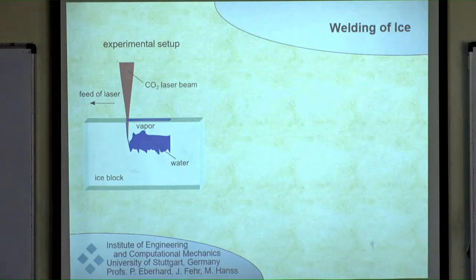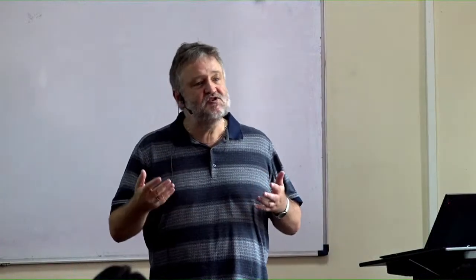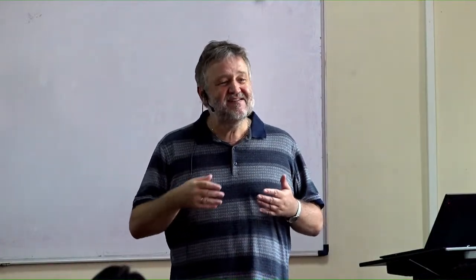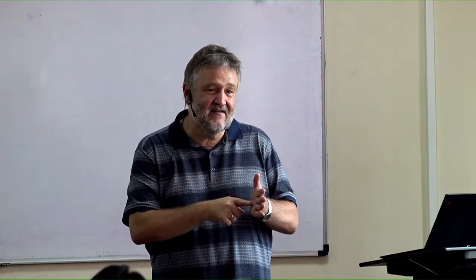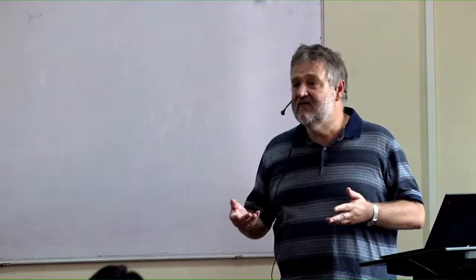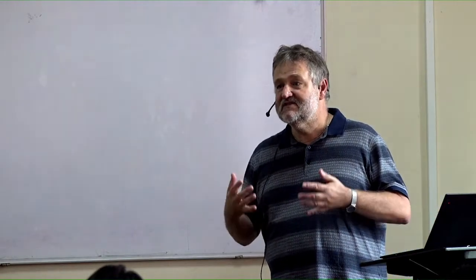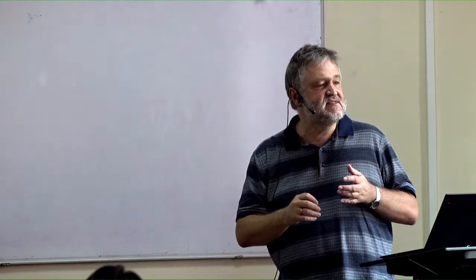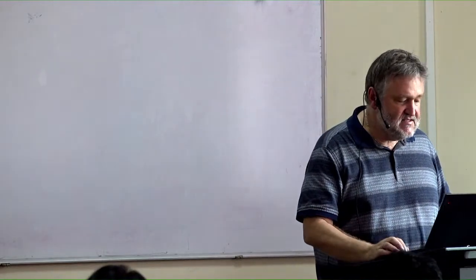One option which is quite surprising is welding of ice. Ice has quite similar properties to aluminium. So if you compare welding in ice and welding in aluminium, the behavior is very similar. Ice has the nice advantage, of course it's cheap, but even better, it's transparent, so you can look inside the ice, which you cannot in aluminium. There are possibilities to make X-ray investigations, for example. There you can also look into workpieces, but ice is of course much nicer and easier to use.